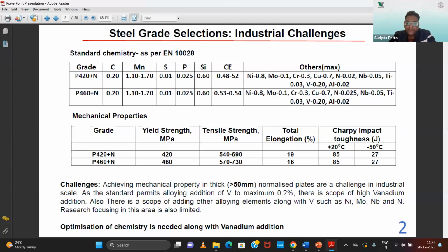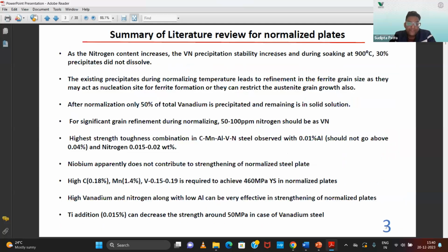So normally these steels are preferred in normalized condition, because in normalized condition toughness is also very high, and the requirement of strength and toughness is given here. You can see minus 50 degree 27 joule impact toughness is required, and 460 MPa YS is required. So this is the chemistry standard as per EN 10028. So you see there is a scope of vanadium addition of 0.2%, and there are other alloying elements also. But we will try to develop this steel with vanadium and nitrogen.